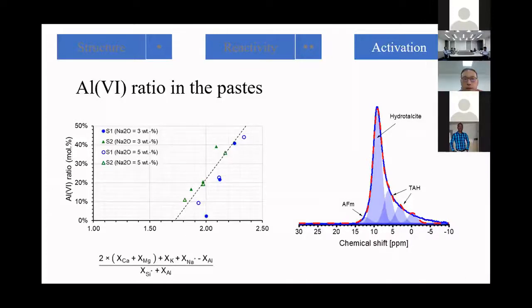And this 6-coordinated ratio in the paste can be further deconvoluted into different hydration phases, like AFm, but it is just in a small amount. Also, hydrotalcite is the main alumina-containing hydration product, along with the so-called pseudo aluminate hydrate. And this pseudo aluminate hydrate is actually not a new hydration product. It was a misunderstanding previously, and actually it is the 6-coordinated alumina in the C-S-H gel structure.